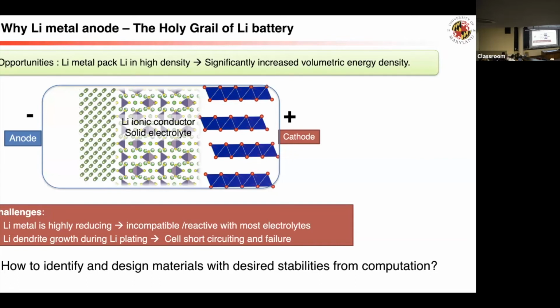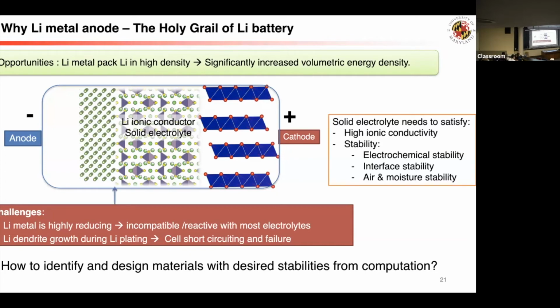Lithium metal has a lot of problems with liquid electrolyte, and with solid electrolyte we also face a similar challenge, because lithium metal is very, very reducing. I think it's the most reducing alkali metal. So it is indeed reactive and incompatible with a lot of materials, even ones as stable as oxide or fluoride. And another issue is dendrite formation.